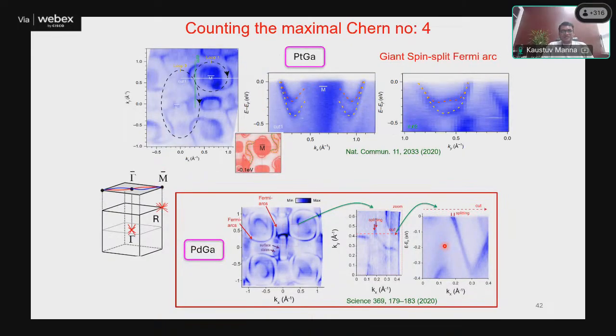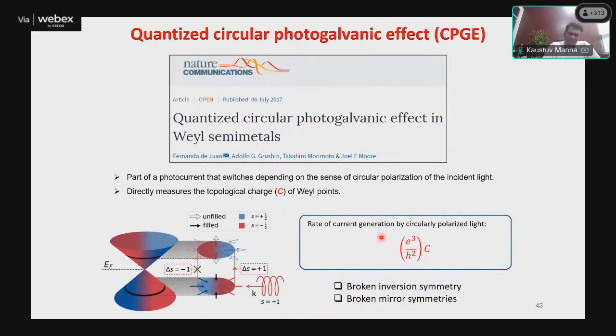Okay. Next, counting of the Chern number, whether the Chern number is 2 or 4. For that, what you have to do is look at this Fermi arc, whether it is 1, 2 or 4. So for that, what we do is a deep energy dependent cut. And we can clearly see the splitting. So 1, 2, 3, 4. 4 number of Fermi arcs, so Chern number 4. This is what we have proved in this paper, as well as in the Science paper, where we have shown the splitting. So this is how we prove that yes, we have Chern number 4 experimentally proved, and we have the chiral topological materials where we have the Fermi arc, and you can control those Fermi arcs with structural chirality, not magnetic field.